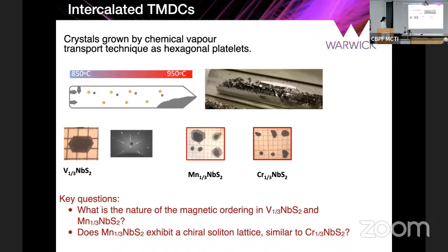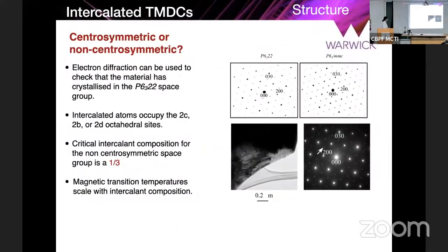So the key questions were, what's the nature of the magnetic ordering in the vanadium niobium sulfide? Because there were conflicting reports in the literature. And then for the manganese one-third niobium sulfide, which for all practical purposes is very similar to the chromium one-third niobium sulfide, whether this exhibits a chiral soliton lattice or not. So that was the main focus of our investigation.